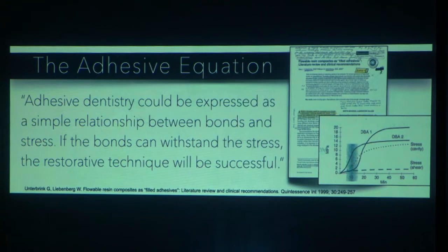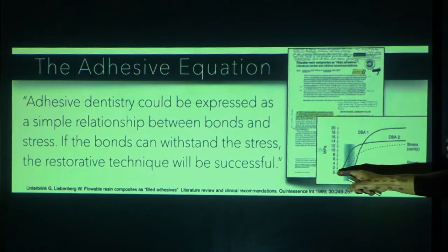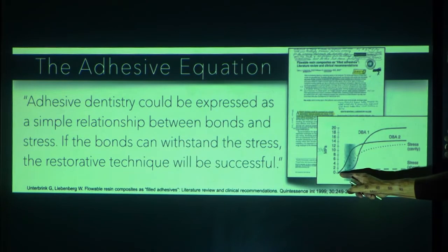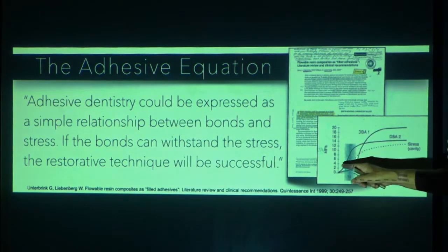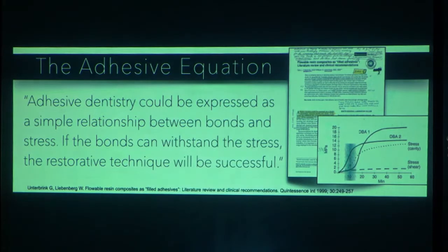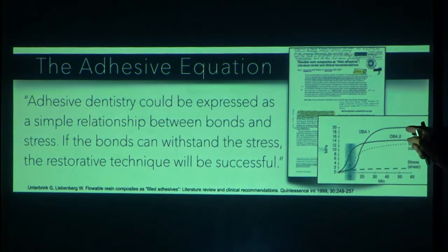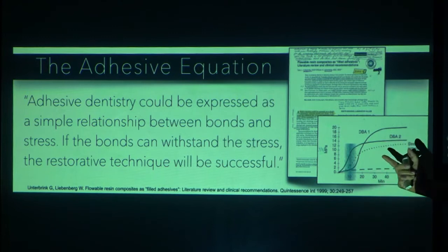So this paper that was published in 1999 by my second mentor that I've had in adhesive dentistry, the first was Ray Bertolotti, and this was Gary Unterbrink. He's still alive, retired in Croatia. But Gary Unterbrink and Bill Liebenberg summarized three papers from a team out of Amsterdam, a polymerization curve. If you have a slow initiation of your polymerization, and then you get to a high bond strength, that's just a function of the chemistry of that dental bonding system.